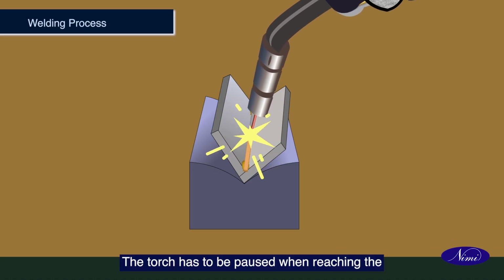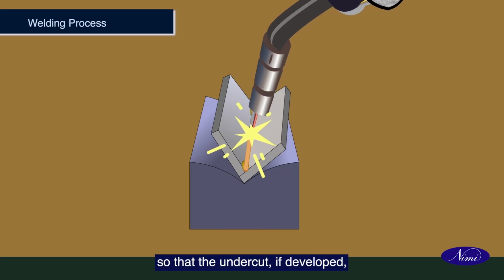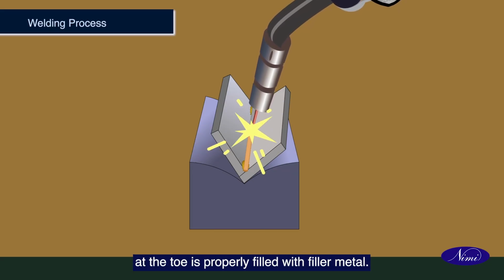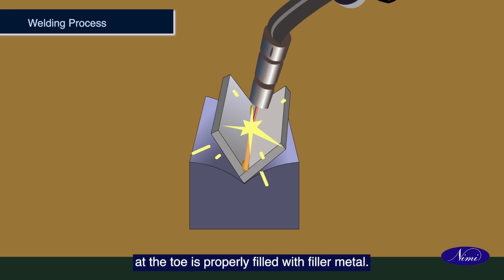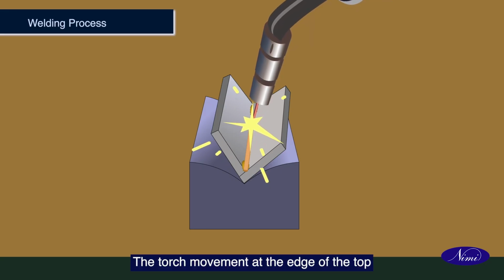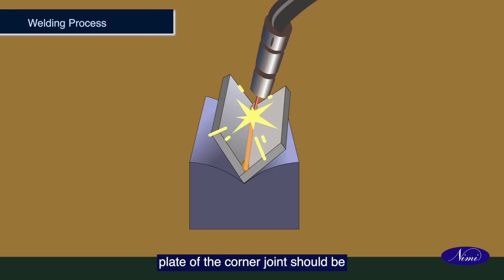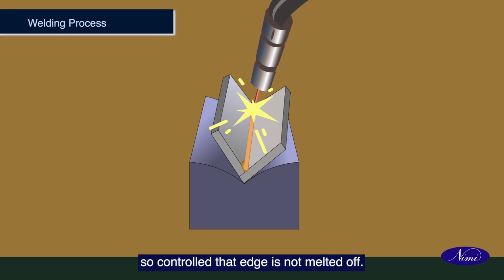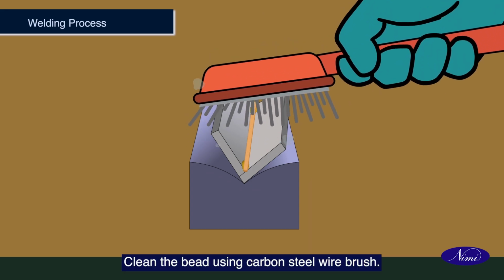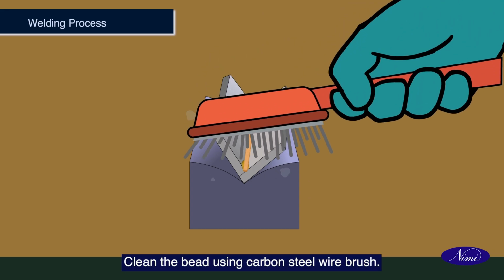The torch has to be paused when reaching the bottom toe of the weld for a short period so that the undercut, if developed, at the toe is properly filled with filler metal. The torch movement at the edge of the top plate of the corner joint should be so controlled that the edge is not melted off. Clean the bead using carbon steel wire brush.